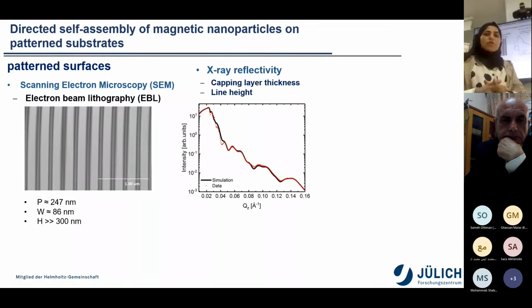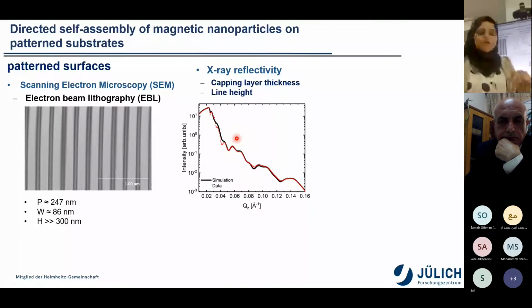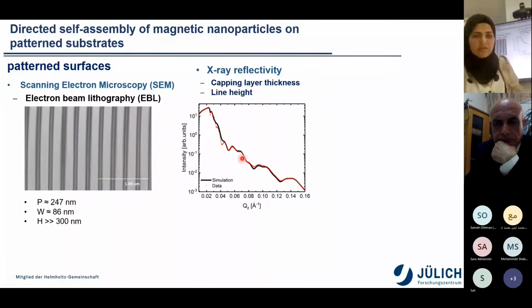In order to get information about the groove depth and the silicon capping layer, we performed X-ray reflectometry, and we end up with two different oscillations, which come from the two different oxide layers covering the two different depth profiles. As is clear from the scanning electron microscope image, we also have another line located between these two main lines.